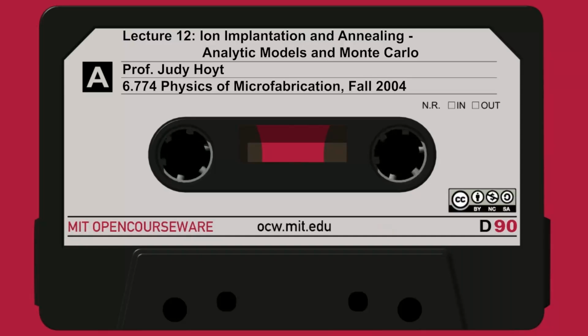And so the dose that penetrates the mask, I can just substitute that in. All you need to do is integrate this little red region, which is given by this. It turns out to be a complementary error function. So you can actually figure out how much made it into the silicon. Generally, you design the mask so that it doesn't make it in.